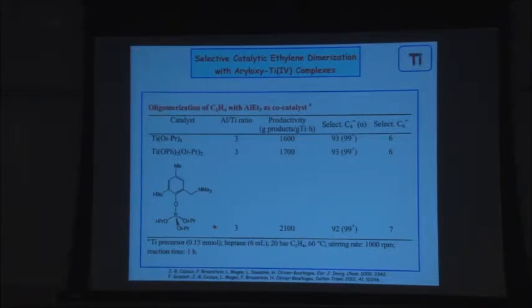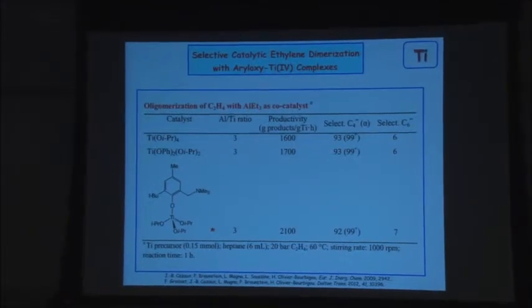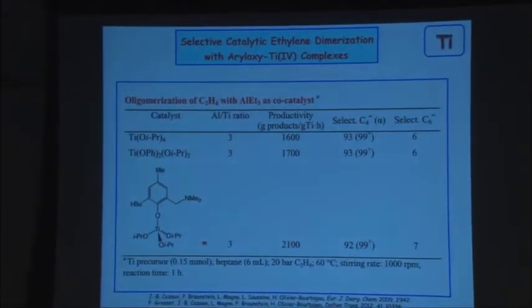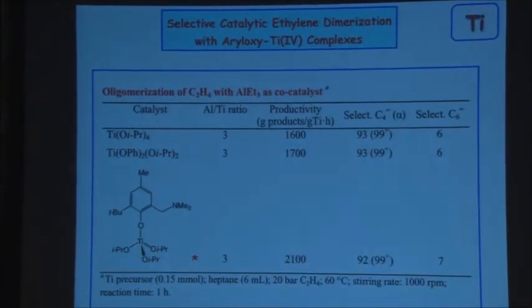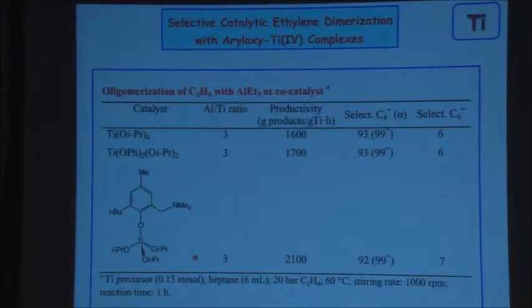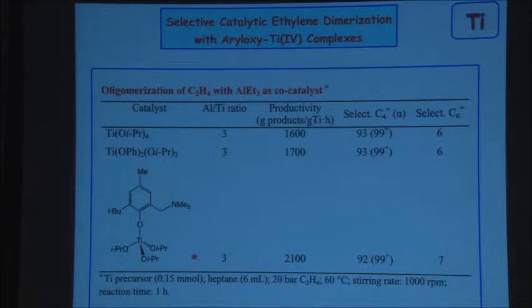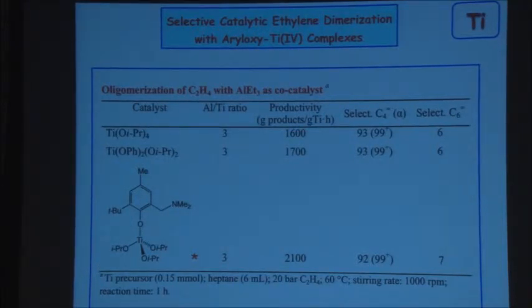And if you look at the productivity in terms of gram per gram titanium per hour, we were quite happy to see that the most active was precisely the one which we suspect has hemilabile behavior. And in terms of selectivity, all of them are very selective for C4 alpha olefin, for 1-butene, terminal alpha olefin, much more than for C6. So basically, you have a very selective catalyst for ethylene dimerization into 1-butene.